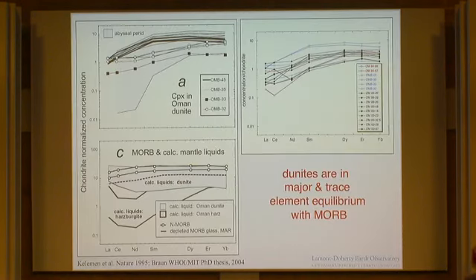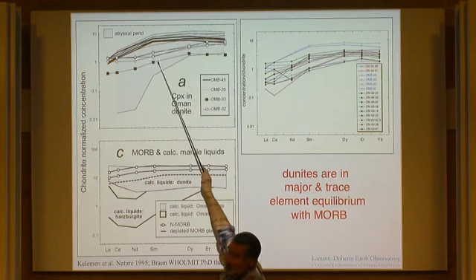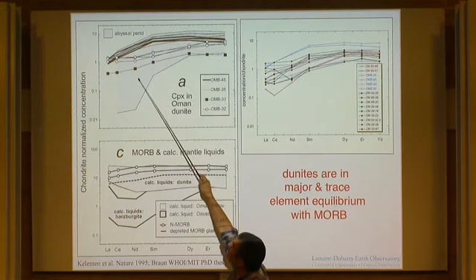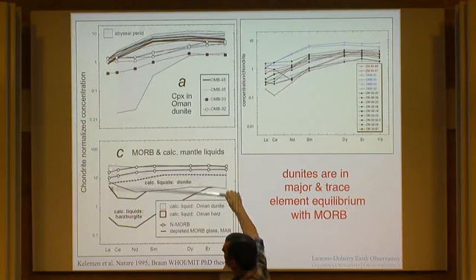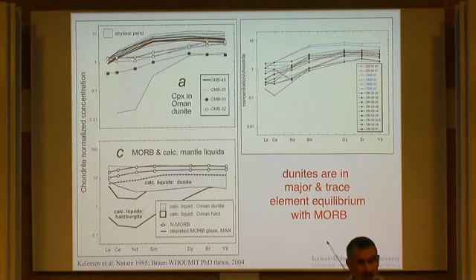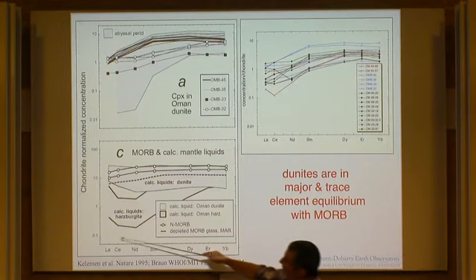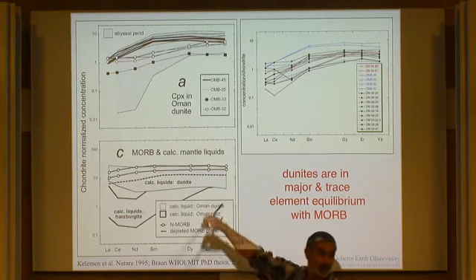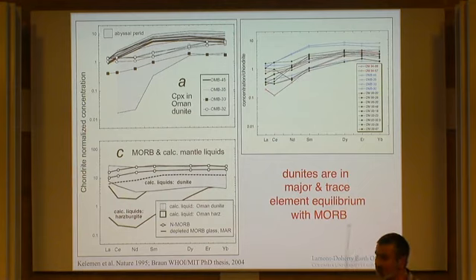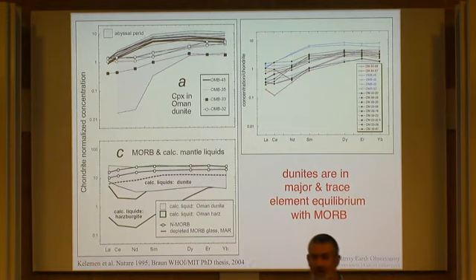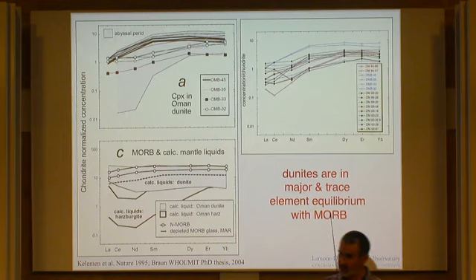Whereas when we look at little bits of clinopyroxene in the dunites, we see something quite different. Here are analyses of a bunch of clinopyroxenes in 4 samples, and we then went ahead and published this. You can calculate liquids in equilibrium with these clinopyroxenes. They look like the lavas that form the crust in Oman, and they look like mid-ocean ridge basalts in this kind of diagram, with the caveat that there are 3 orders of magnitude of concentration on this axis. So the dunites are the conduits for the kind of melts that form the crust, and they're saturated only in olivine. They don't have any orthopyroxene in them. So they not only preserved trace element disequilibrium between the melts that went through them and the mantle around them, but they also preserved major element disequilibrium between these olivine-saturated melts in the cores of the dunites and the pyroxene-bearing rocks around them.